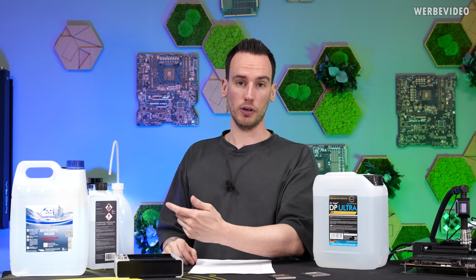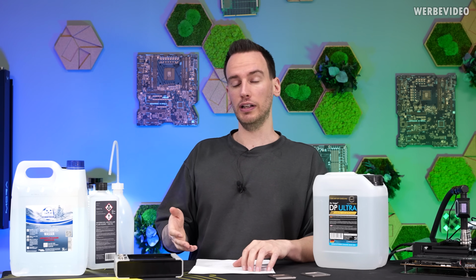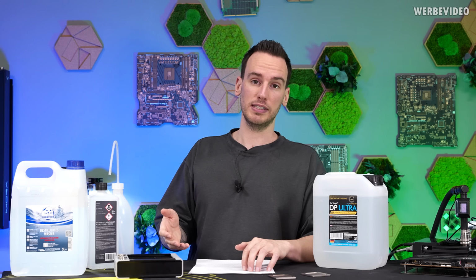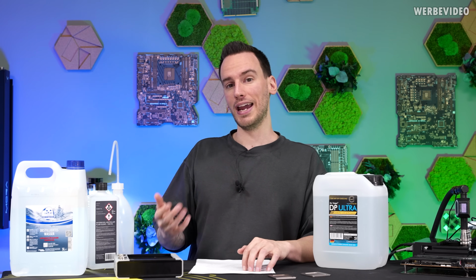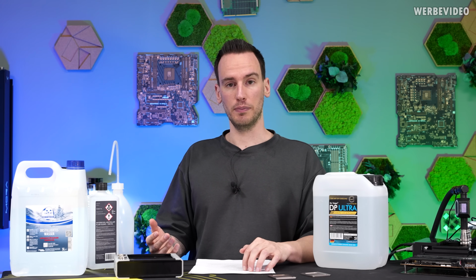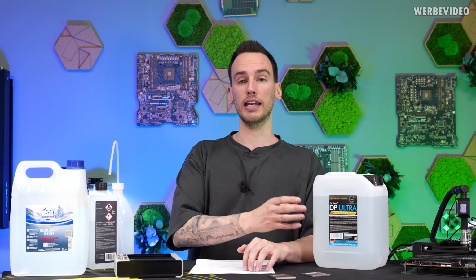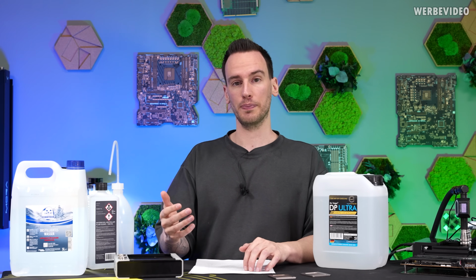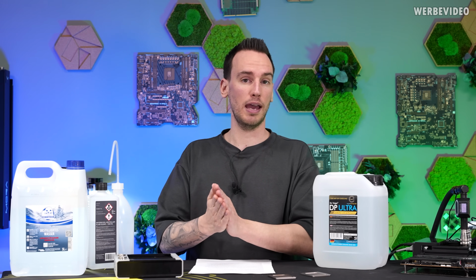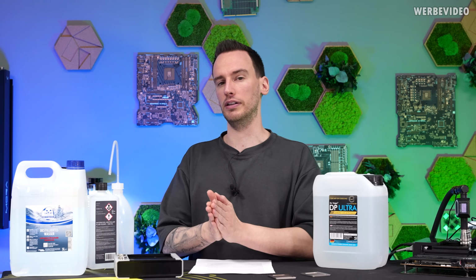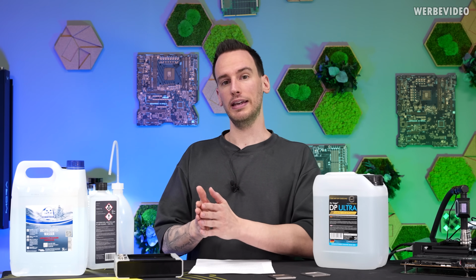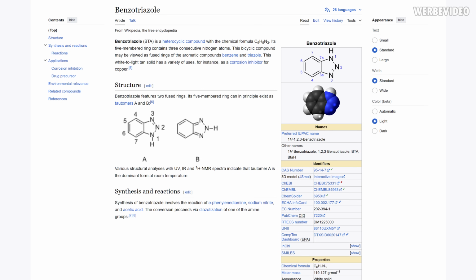Without this, the distilled water can drop more easily in pH value, going to maybe between 5 and 7, which is then even more attacking the metallic surface. But what is helping against the corrosion is that the glycol sticks to the metallic surface, thus protecting it not only chemically, but also like a physical barrier in between the distilled water and the metallic surface. The benzotriazole that is inside the DP Ultra works in exactly the same way.